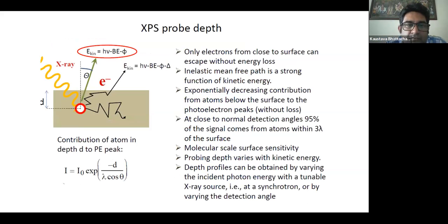Okay, so now we almost always hear that X-ray photoelectron spectroscopy is a surface technique. Why is it a surface technique? Let us clarify that first. It is a system where we use X-ray as a source. The penetration depth of the X-ray is infinite, because the X-ray as such is a chargeless and massless entity. It can travel to any extent, although obviously it depends upon the energy of the X-ray. Therefore, XPS being surface sensitive is not dependent upon the penetration depth of the X-ray, but upon the ejection of the electron.